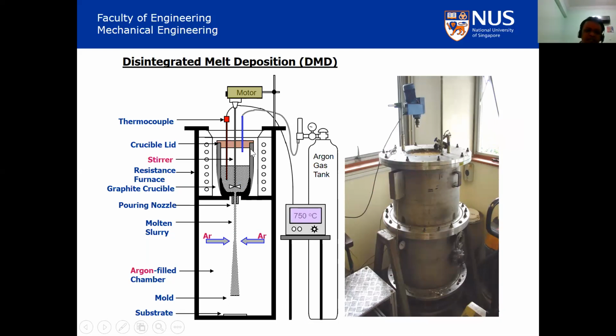What we do is that we take a graphite crucible, we put the material in the crucible, we use a resistance heating furnace, very cheap, and take it to 750 degrees centigrade. We stir the material with the reinforcement, we bottom pour it, and when the metal is pouring, you hit it with argon gas jets to disintegrate it, and then you deposit that into an ingot. And a typical facility which we got for about $25,000 is shown here in the lab.